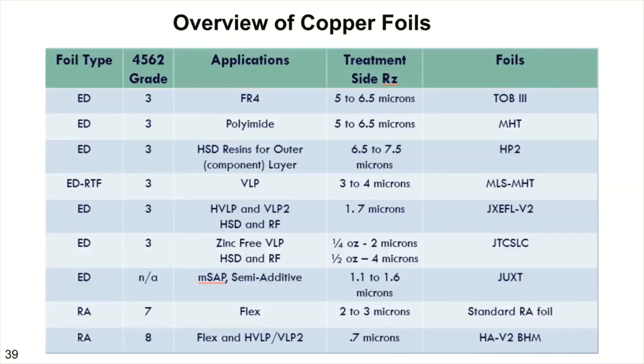With this chart, just an overview of some of the copper foils available to us — you can see on the left side the foil type, whether it's electro deposited, reverse treated, or rolled annealed, and some of the applications whether it's standard FR4 or polyimide.